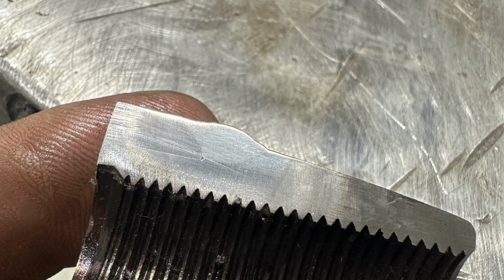The 1/8 inch rod was a little bit harder to control than a 3/32, simply because, well, you're putting down more metal and you're running at more amperage. But based on the profile of both of them, I'd much rather use the 1/8 inch rod, which makes sense because this is 1/4 inch plus steel, so you're going to need more amperage arguably.